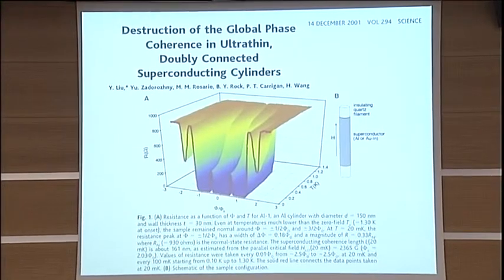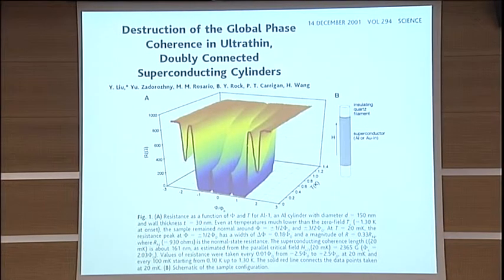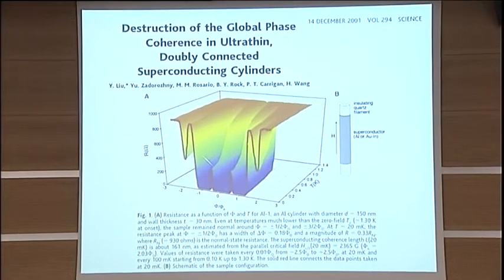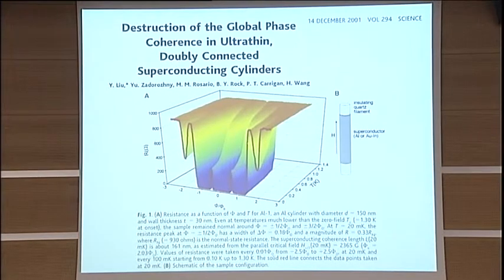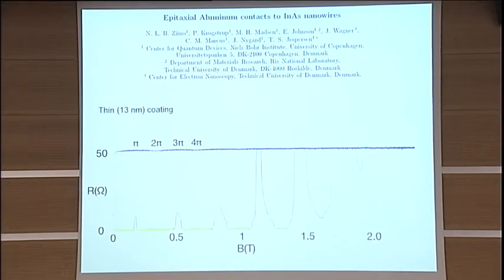Here again, an interesting result is obtained. If you go back in the literature, you can see that if you wrap a superconductor around a wire and you put a magnetic field through the axis, you get a kind of Little-Parks effect in which the superconductivity is destroyed when a half a flux quantum threads the wire. And this was something that was well studied in this paper and in others in the literature. And in this case, you can see that you can destroy superconductivity but bring it back to life. In the case of ours, it's quite hard to see, but that's okay.